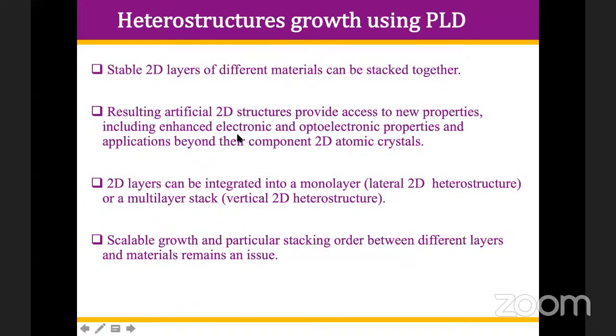So in this case, we again tried to use the pulsed laser deposition technique so that stable 2D layers of different materials can be stacked together, because by PLD, as we mentioned earlier, we can grow the stoichiometric material in a controlled manner, and put one over the other. The resulting artificial 2D structure provides access to new properties, including enhanced electronic and optoelectronic properties, and applications beyond their counterparts. That means if we are using two different compounds, then the composite material or the heterostructure will give better results as compared to the individual ones.